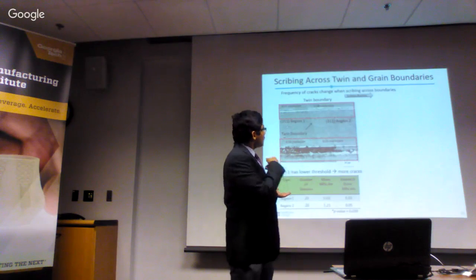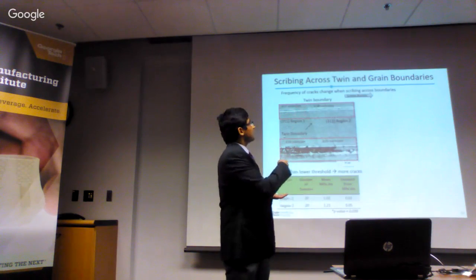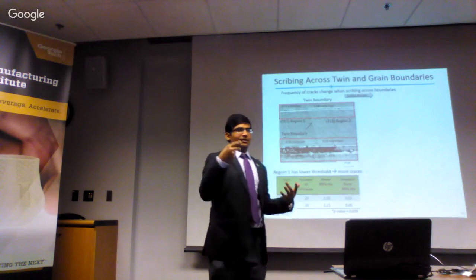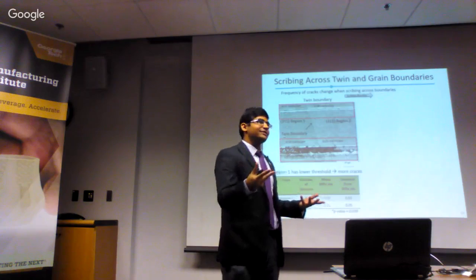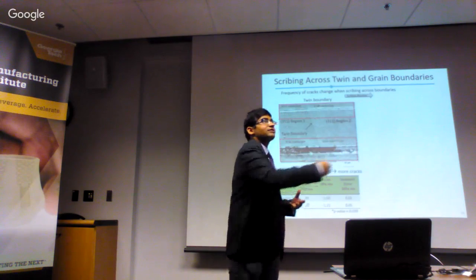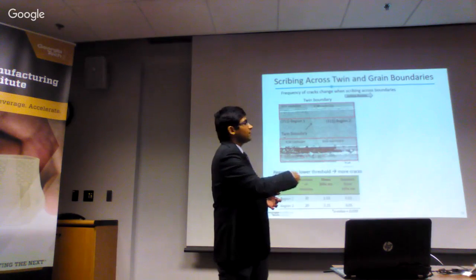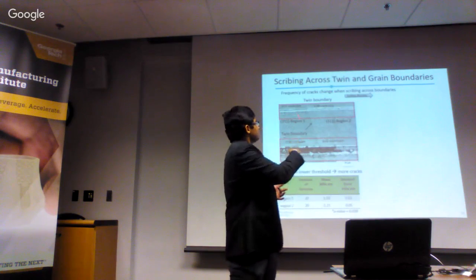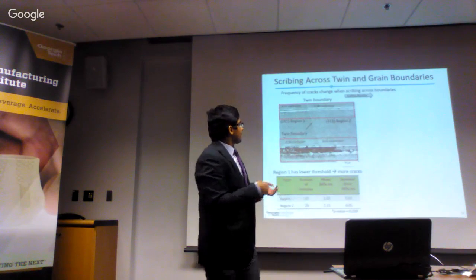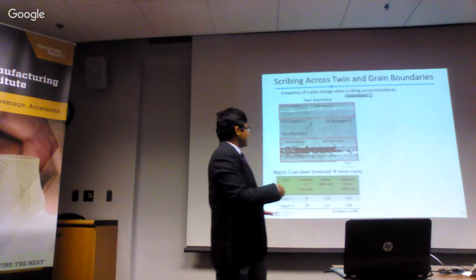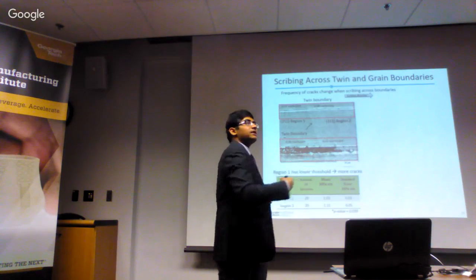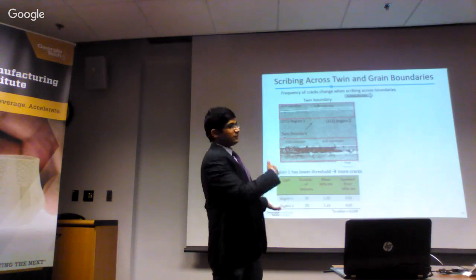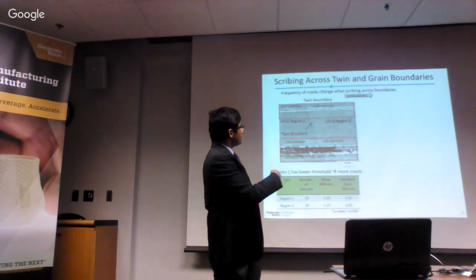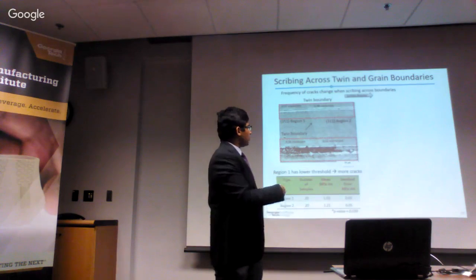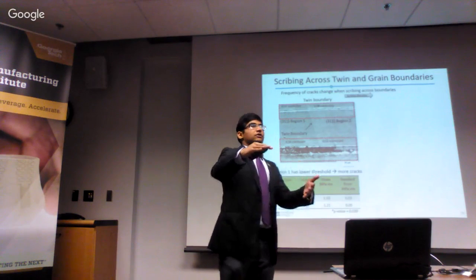However, we found that across the twin boundaries, the number of cracks per unit distance of scribe, that's a metric I term as cracking frequency, the number of cracks per unit distance of scribe length, changes very abruptly across the boundary. That happened for multiple scribes, like only 2 are shown here. And the reason we see this is because of the fracture strength changing also abruptly across the boundary. We found the fracture strength by Vickers microhardness indentations to be lower on this region 1 of 311 grain, 1.03 MPa meter compared to region 2,